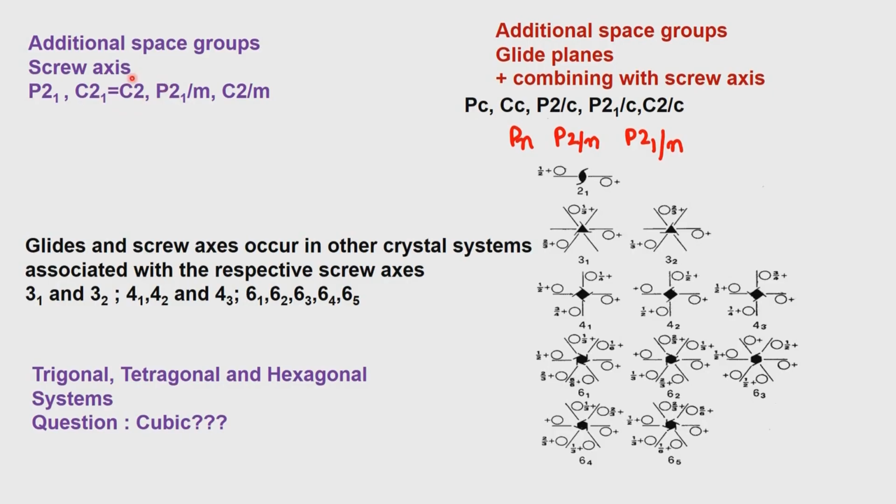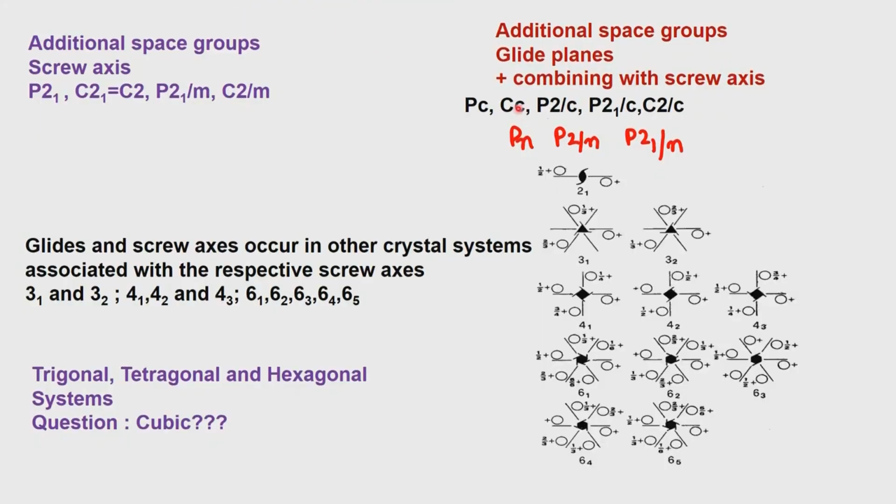So therefore, the secondary interaction can be ignored because it is already built in to the primary interaction. So when we say a space group is, let us say, CC, the operation of this capital C is more crucial than the operation of the small c. That is how, for example, we will not have a glide associated with C centering, and that is where we see that the importance of the dominance of the lattice type comes first. This is something I thought you should notice before we go further.